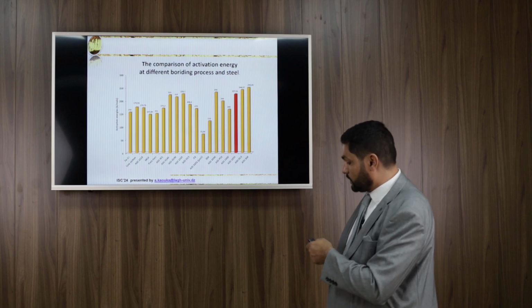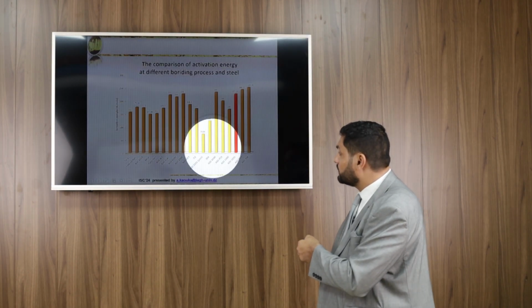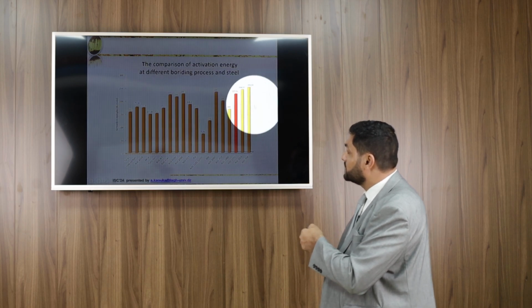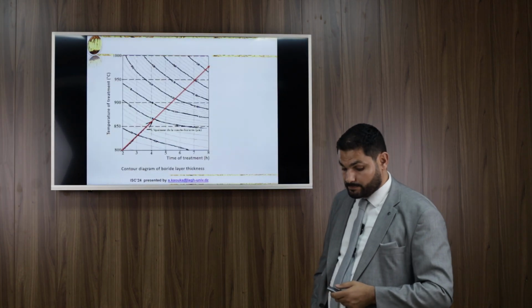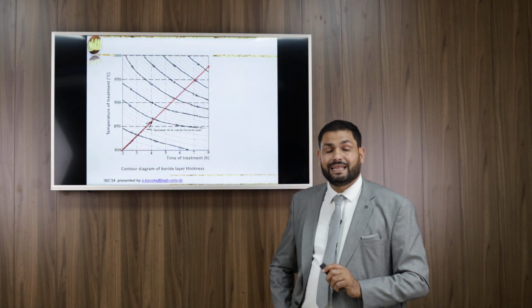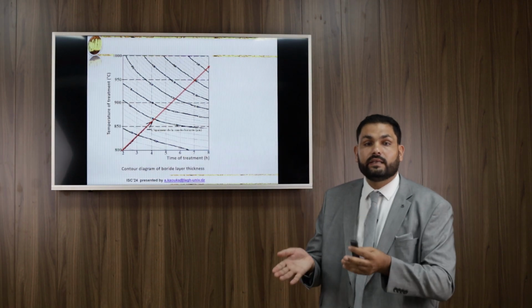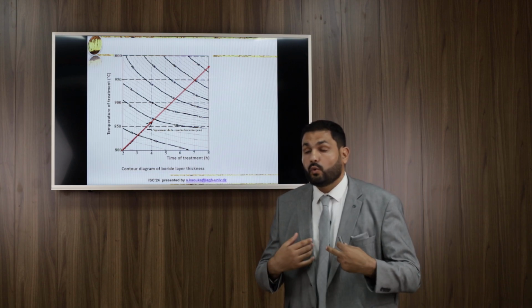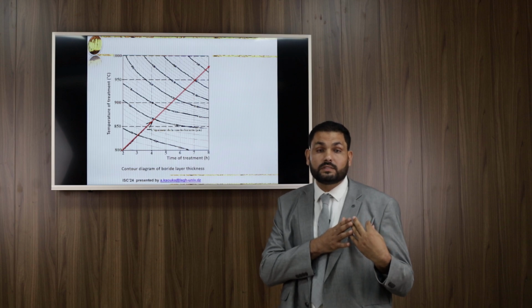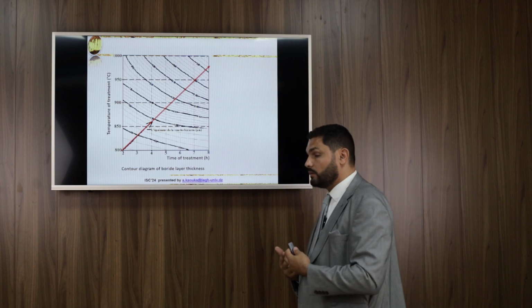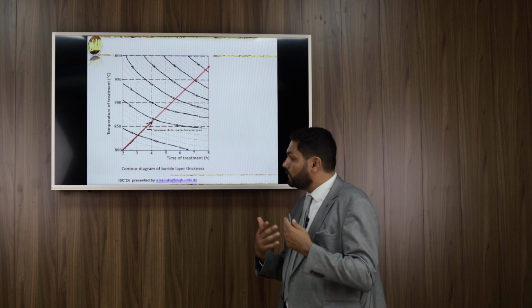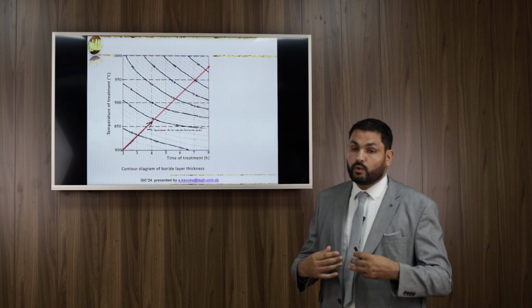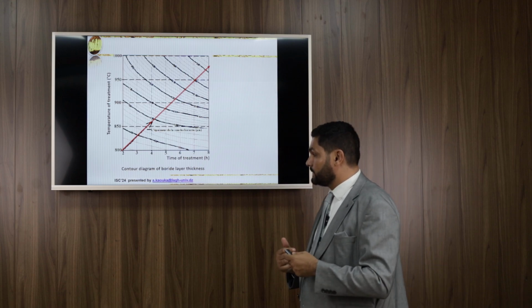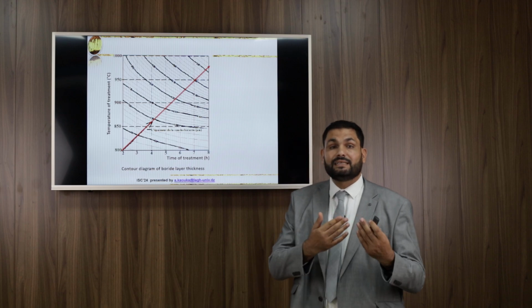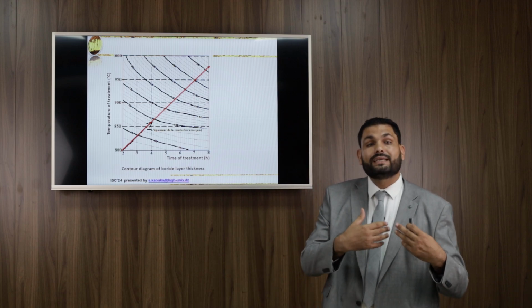So we compare also our results. The activation energy in red color is compared with that we have in the literature. So it's important, and this is the best one, I think. And also an important result is that we can predict the thickness of boride layers that we will obtain with our experimental results. With the software, we draw the contour diagram of boride layers. So we have temperature as a function of time of treatment, and we can predict the thickness of boride layers that we can obtain.